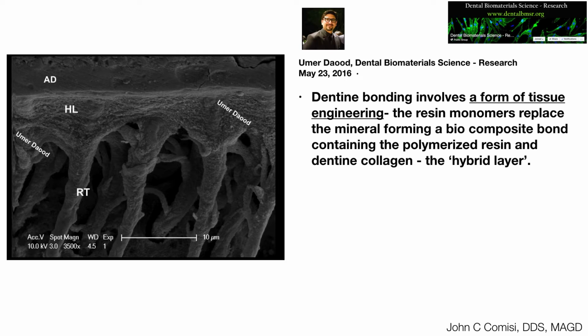Our brilliant colleague, Dr. Umer Daood, PhD of adhesive dentistry, posted this image and these words in the Dental Biomaterials Science Forum that we participate in. Umer stated so very clearly that dentin bonding involves a form of tissue engineering. That is, the resin monomers replace the mineral, forming a biocomposite bond containing a polymerized resin and dentin collagen, otherwise known as the hybrid layer. The resin-dentin bonding is achieved via self-etch or etch-and-rinse adhesives by infiltrating into the collagenous matrix and dissolving minerals, up to a depth of almost 10 microns in the case of etch-and-rinse bonding systems.